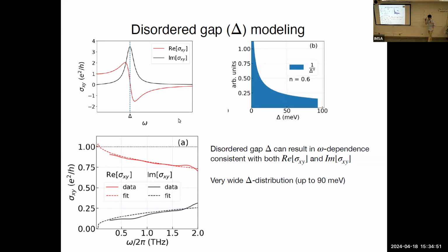And yeah, before theoreticians say, oh, this is wrong and you should use the mean field theory, I would say yes, you're right, but it's not so easy to use mean field theory. But we've come up with a distribution of single gap values, each of which has this sort of frequency dependence, and we fitted our data. And as you can see here, you can have a distribution which will qualitatively describe all the features in the data. So you will still have a DC quantized effect in the DC limit, and it will have decreasing frequency dependence in the real part and increasing dependence in the imaginary part.